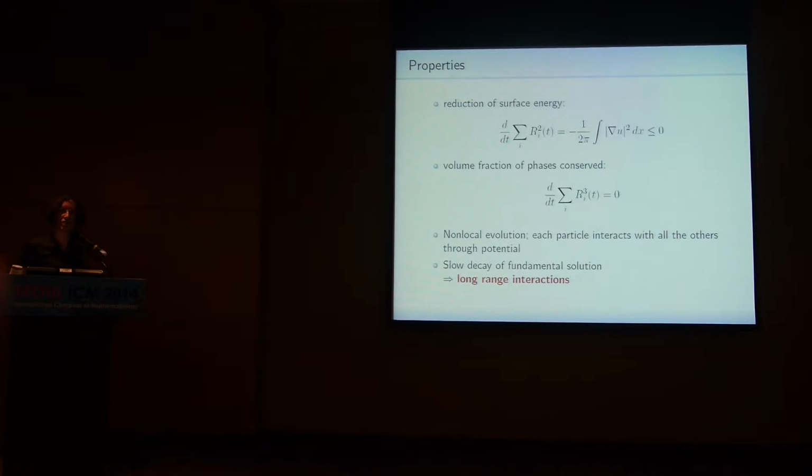One can easily check it has the following properties. The surface energy is reduced in time, where the surface energy here is just proportional to the sum of the radii squared, and at the same time the total volume covered by the particles is preserved.